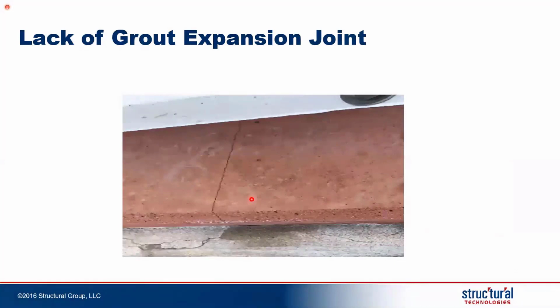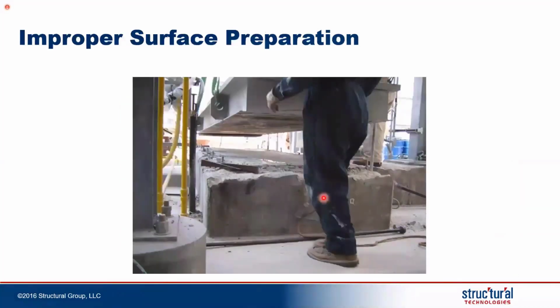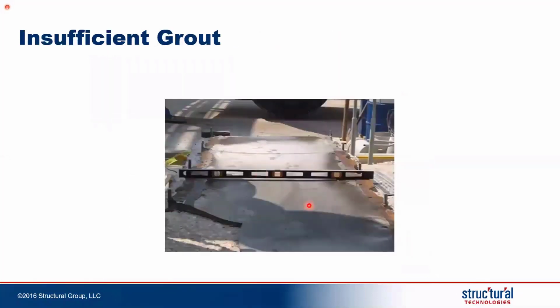We see this quite often on some larger pump base foundations where the grout does not have expansion joints, and you can get a crack in the top of the grout that extends down into the concrete. Here's an example of a pump base that was regrouted and started up and had immediate vibration. And when the pump base was lifted off the foundation, none of the grout was stuck to the bottom of the base plate, implying that the base plate surface was not prepared properly.